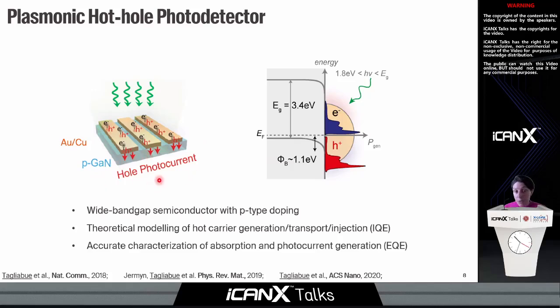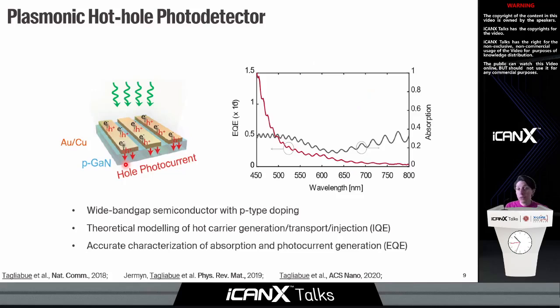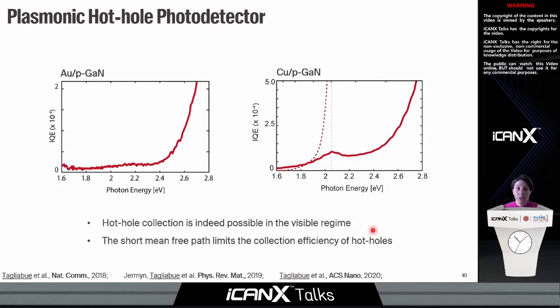In fact, when in experiments we measure a photocurrent, we are making an integral measurement of all of the carriers that have been able to overcome the metal semiconductor interface. In order to compare experiments to theory, we also had to realize really clean interfaces between the metal and semiconductor and precisely characterize both the absorption and the photocurrent generation as a function of the photon energy. So for example, here you can see the results for the absorption in gray and the external quantum efficiency of our device as a function of the incident wavelengths. With these two pieces of information, we are then able to extract the internal quantum efficiency of the system, which is the quantity that we can more easily compare to the theory. So what you see here are the two internal quantum efficiencies as a function of the photon energy for two different devices, one which is a gold p-GaN device and one is a copper p-GaN device.